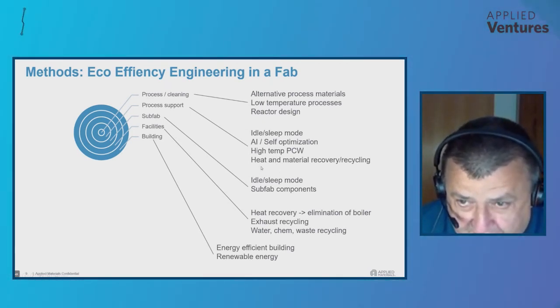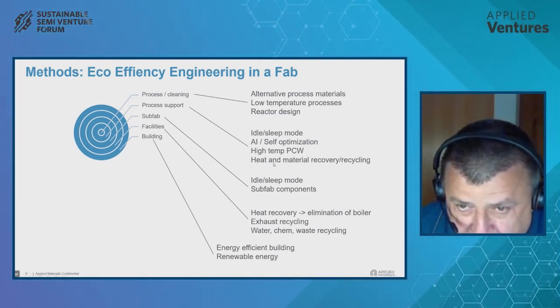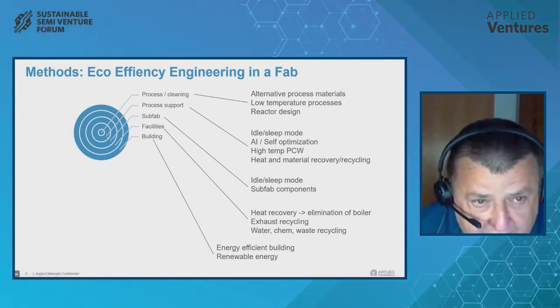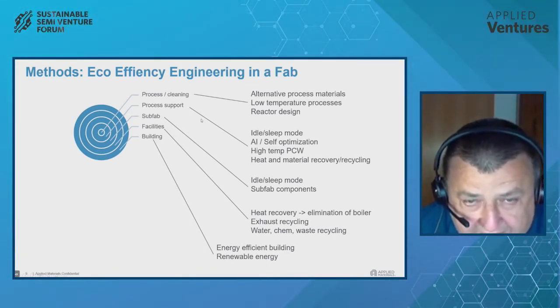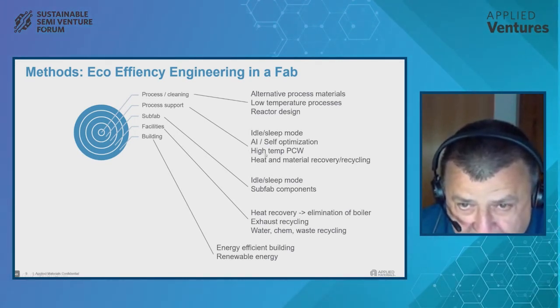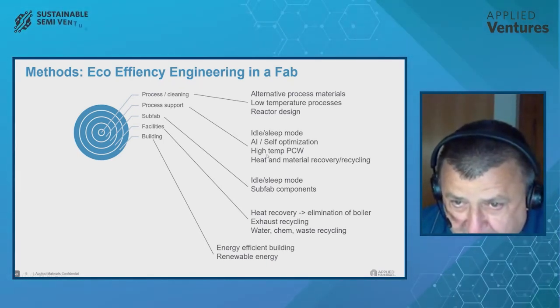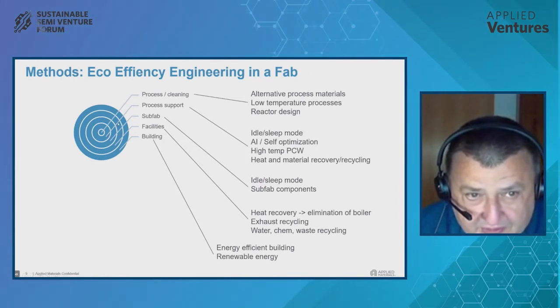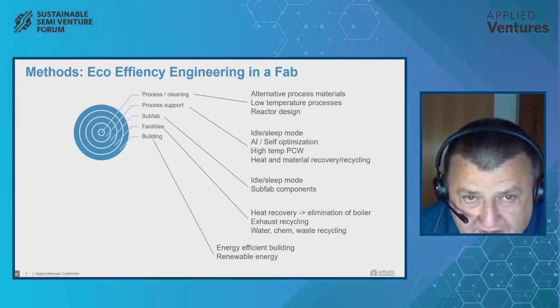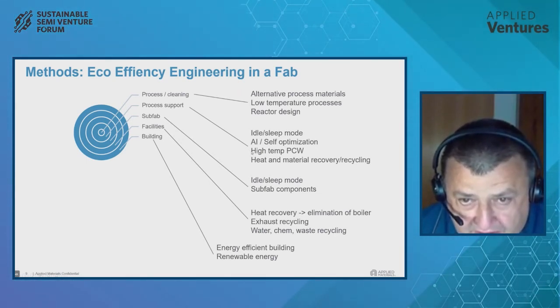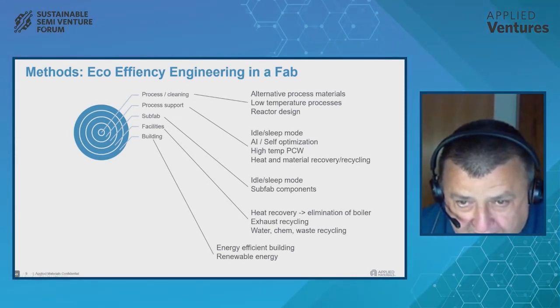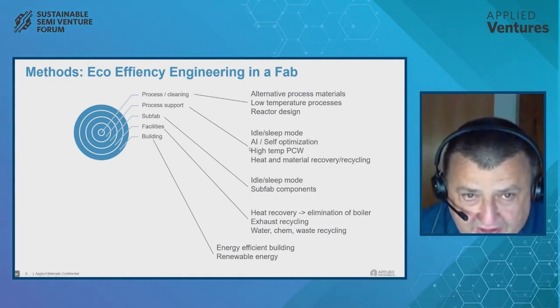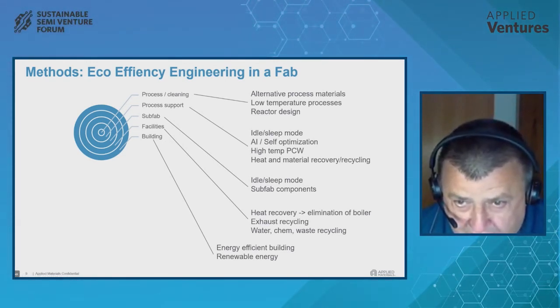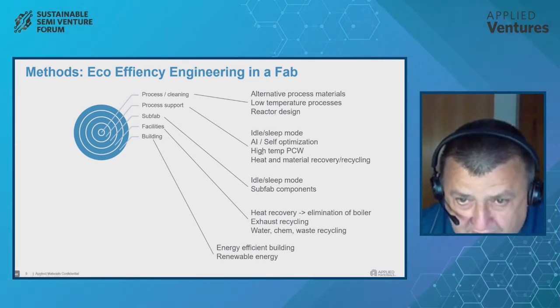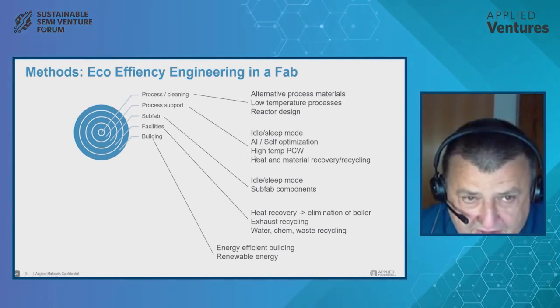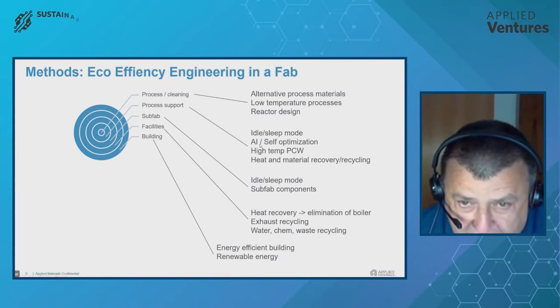From the innovation perspective, an area where we can really also make a big change is to recover heat in our process. Now, heat recovery is easy if you have a high temperature, and heat recovery is easy when you have not all these aggressive materials we are using in the reactors. Our heat is coming at between 40 and 80 degrees C. Between 40 to 80 degrees C, we can have heat available in less aggressive chemistry environments, but there are not many technical means today which can utilize those low temperature heat sources, as big as they are. So innovations in that field, I would really appreciate. This is something where you can make a big change in the semiconductor industry.